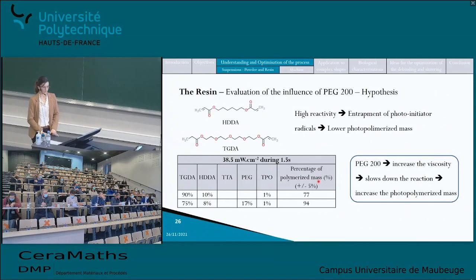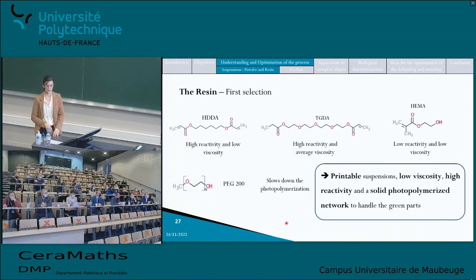So finally, that brought me to my final selection of the monomers that were going to compose the different resins. I chose the HDDA for its high reactivity and low viscosity, the TGDA for its high reactivity and average viscosity. I also decided to pursue the experiment with the HEMA, even though it has a very low reactivity, but also because it has a very low viscosity. And I decided to keep the polyethylene glycol 200 that can slow down the photopolymerization and also act as a plasticizing agent.